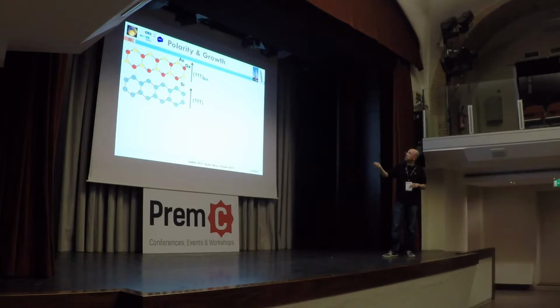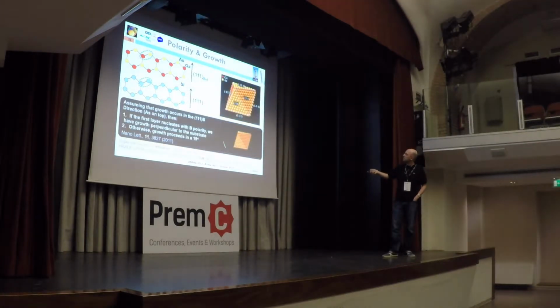So this is the typical 1-1-1 direction. I told you that it can be terminated in arsenic or in gallium, and only the anionic polarity is the one that is giving rise to the growth of these materials. So you can understand that if this is a typical octahedra composed of 8 1-1-1 planes, only the ones terminated in yellow color, that is the arsenic, will allow the growth.